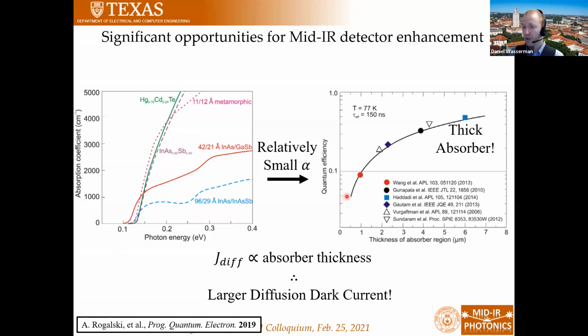And so, well, you might say, who cares, right? I'll just make my device thicker. Maybe it doesn't absorb as well, I'll just make a thicker device. Well, there's a couple of problems with that. One is that the thicker you make your device, you still have to collect those electron hole pairs. So if you generate an electron hole pair deep into your device, it's unlikely that it'll end up being collected at the contacts or at the barrier of the device. So basically you're sort of losing as you go thicker and thicker. The marginal gains keep decreasing because your collection efficiency will go down.